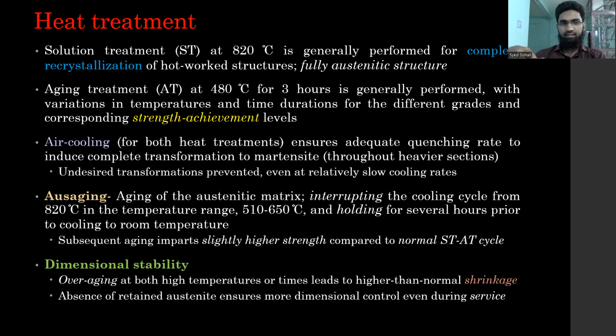So that advantage of not going through undesired transformation is another aspect. Also aging, this is also performed, but this is not generally performed, wherein you have the aging of the austenitic matrix. Basically, what you do is you interrupt the cooling cycle from 820. Once it is taken from 820 down, it is interrupted at 510 to 650, and it is held for several hours at that particular temperature prior to cooling again to room temperature. So this halting and holding is a significant feature of the Ausaging process. And then later on, it is subsequently aged, which imparts slightly higher strength compared to the normal ST-AT cycle, solution treatment aging cycle. This Ausaging aging is able to have higher strength.